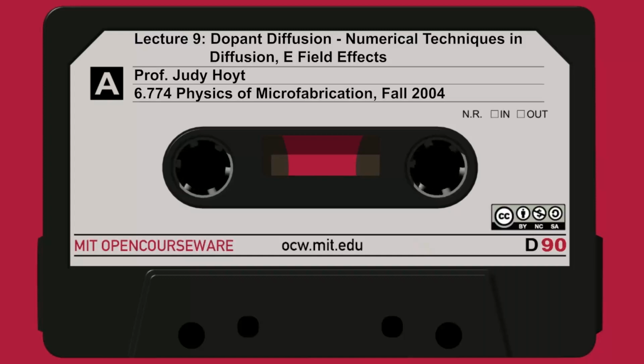I won't derive it here. If you go back to Crank's book or any of the books on numerical methods, you'll find that the method is numerically stable. So it works from a numerical point of view. It gives reasonable answers for a particular condition. When we're doing this solution, we have a condition on a quantity r, which multiplies the concentration change in a slab at a certain time step delta t: D delta t over delta x squared. That multiplier has to be less than or equal to 1/2.